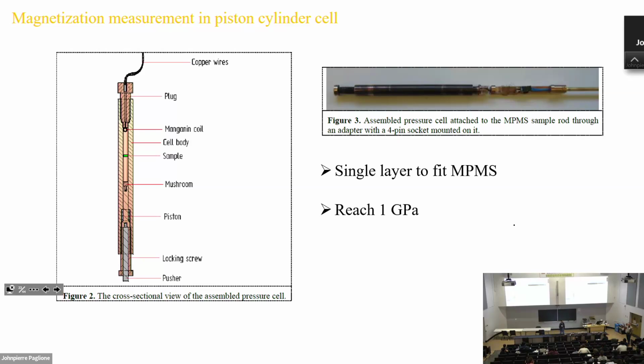So the other way, just for completeness, we do this with the MagLab, for instance. You can do what's called the TDO experiment. Essentially, you wrap the sample in some coil, and rather than trying to measure some kind of magnetometry, you use the TDO technique, which measures the change in inductance very sensitively. And you can do this in a pressure cell, and so on.